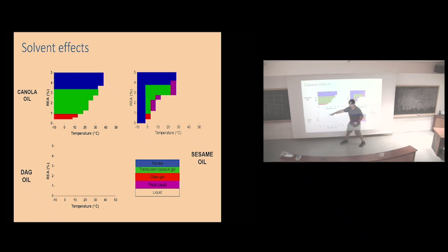You put it in a diglyceride oil, and diglyceride is the triglyceride minus one fatty acid, so it has now an OH, and it's much more polar. And look, nothing. It doesn't gel. So the solvent, I guess it makes sense, right? The solvent plays a role in a gelation phenomenon. So you have to think of the oil as the solvent. And probably if you put it in olive oil, it's not going to work very well either, because the olive oil has many of those minor nice green components that you like for health and taste, and those things are going to mess around with the solubility of your gelling agent.